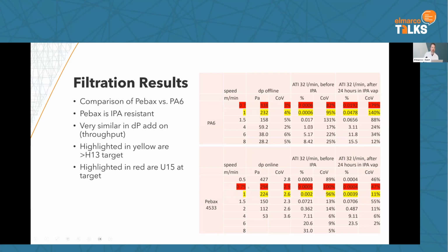Also to note, the line speeds we were running here, you can see the highlighted one in red. The pressure drop, which we can relate back to the throughput, the pressure drop add-on for both of these polymers was very similar. So we're seeing that the throughput is quite similar between nylon and Pebax. So we're not losing anything there. And then you can see that we were able to achieve HEPA, like H13 all the way up to U15, in the flat sheet materials that we're showing here. And that's quite important to us.